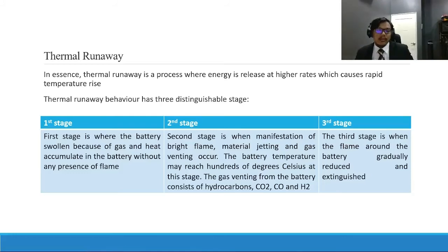Moving on to the next topic, thermal runaway. In essence, thermal runaway is a process where energy is released at higher rates, which causes a rapid temperature rise. Thermal runaway behavior has three distinguishable stages. There are other studies that put thermal runaway in 4 and 5 stages, but personally I prefer 3 stages. The first stage is where the battery is swollen because gas and heat accumulate in the battery without any presence of flame.